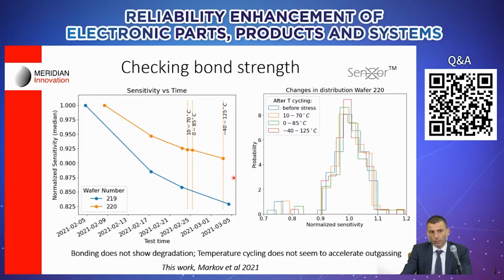As far as sensitivity is concerned, we see that difference from one wafer to another is more significant than what we incur in terms of variation of sensitivity as a result of the temperature cycling. On the right, I show merely that the distribution of the statistics amongst the different dies that have been stressed remains roughly the same. Only outliers that have low sensitivity would be affected somewhat, but not to a great degree.